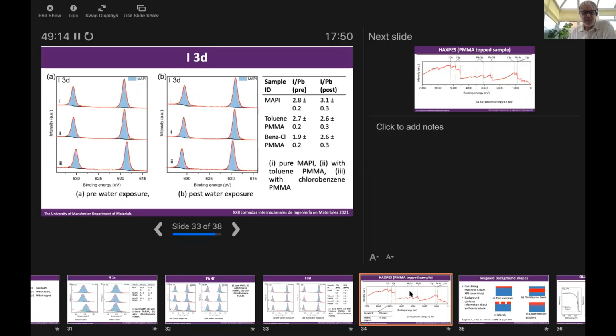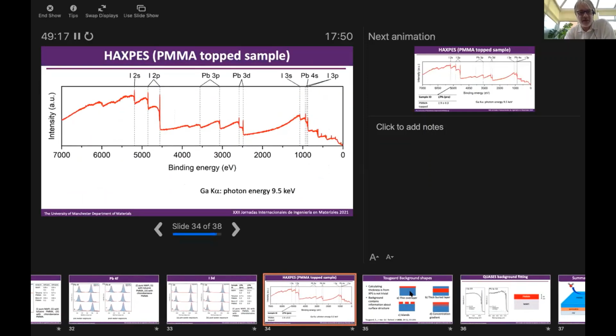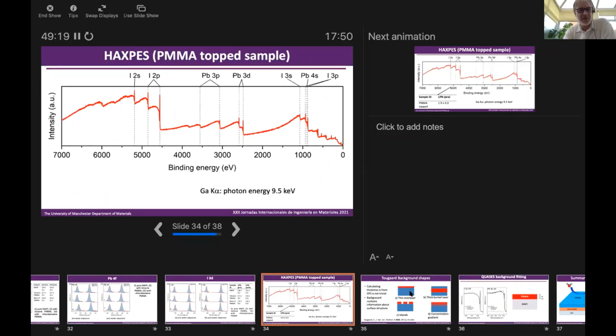In order to look at the PMMA topped sample, we had to use our new instrument in Manchester, which is a hard X-ray photoelectron spectroscopy. It allows us to use photon energies up to 9.5 kilovolts. When we use this, we get much higher kinetic energy of the electrons, which means we can probe deeper into the materials. So rather than 1 to 10 nanometers, we can now get between 1 and maybe 75 nanometers probe depth. With this hard X-ray source, we can now see the lead and iodine in these samples.